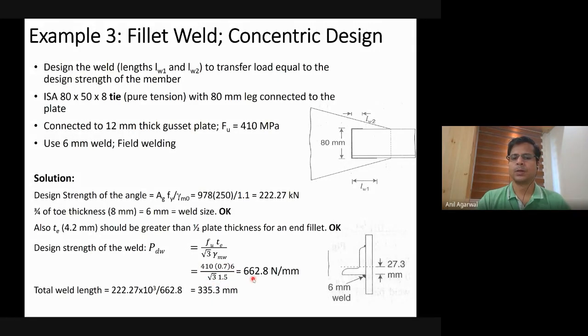So this is obvious. Now you get a strength. In this expression I have not used the length, correct, because I want to calculate the length. So this strength that I'm calculating is for unit length of the weld, 1 millimeter length of the weld. So 1 millimeter length of this weld has a strength of 663 Newton. From there, I know the force requirement, the demand, that is 222.27. So that divided by that and converted to Newtons, 10 to the power 3 divided by 662.8, gives me 335 millimeter length. So the total weld has to be 335 millimeter long.